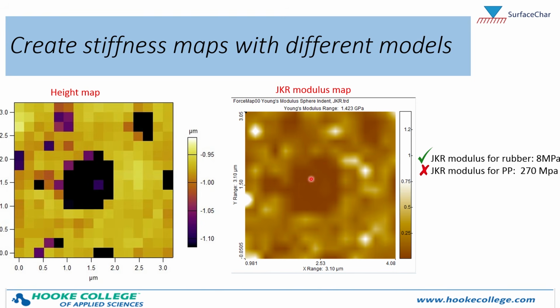Again, because there's such a big spread between these two materials, you cannot make a measurement on both of them with a single cantilever, at least not using its first eigenmode. So this is always a challenge in these kinds of measurements on a heterogeneous sample, which spans a large range. You kind of have to pick which material you want to match the spring constant to. And again, in this case, I matched to the rubber and therefore got an accurate measurement on the rubber.